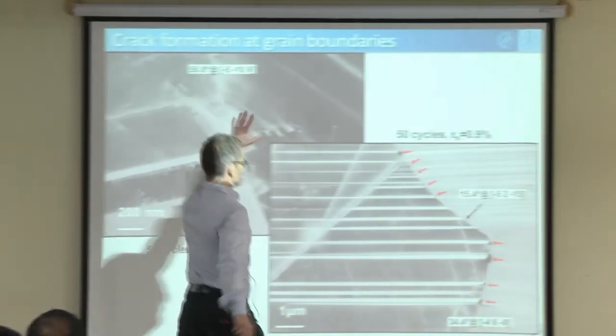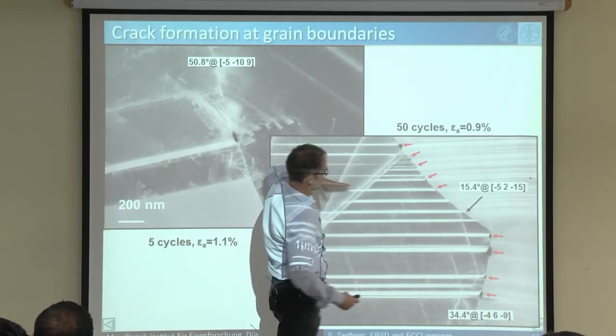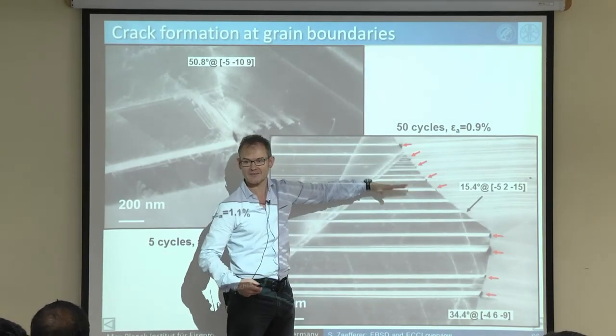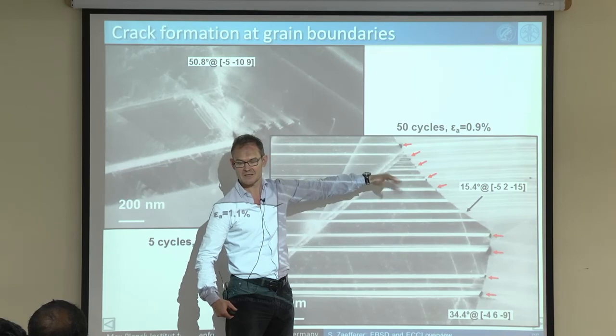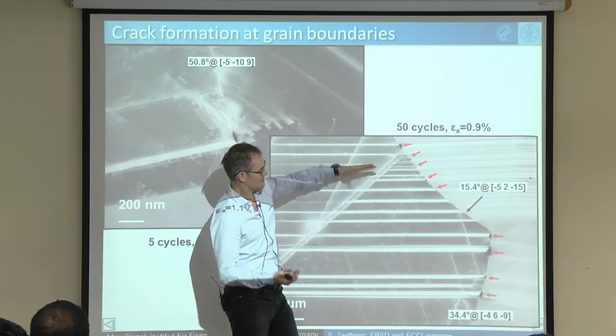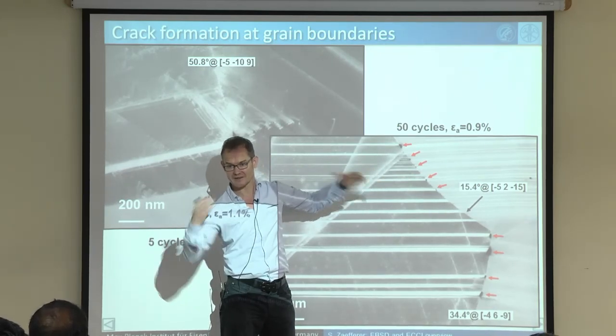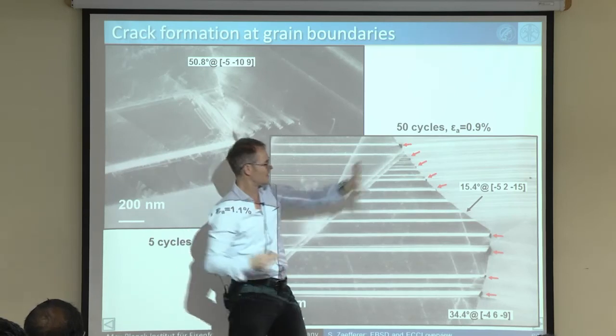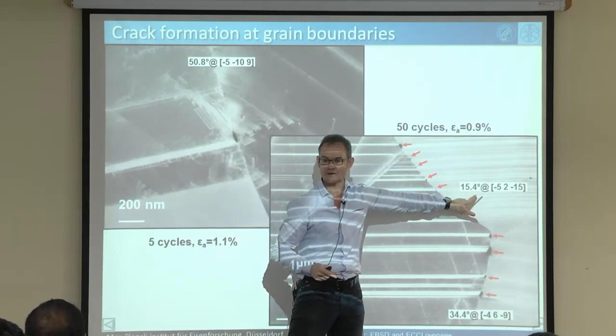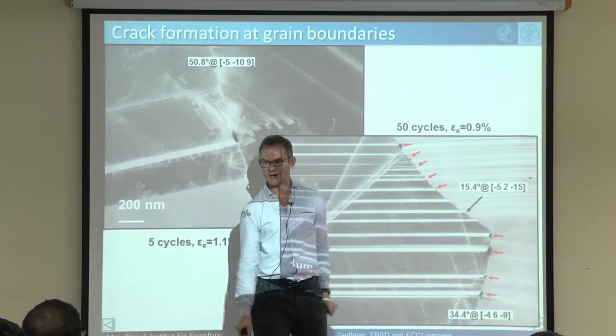This martensite in the grain on the left and the right, they are almost in the same directions. You mean here and here? By chance, I think the 001 planes are similar, or the 111 planes in the austenites, you have some which are relatively similar, but the misorientation is 15 degrees. So it's not so similar actually.